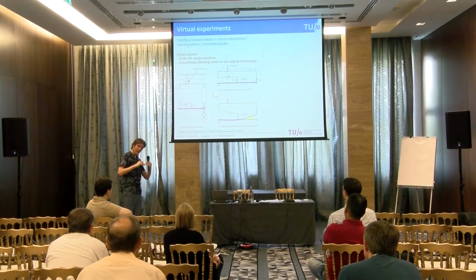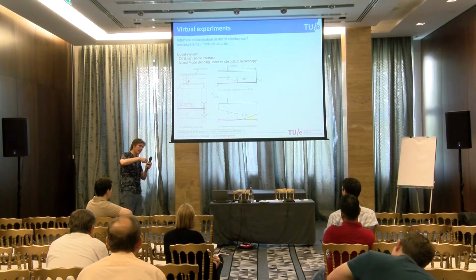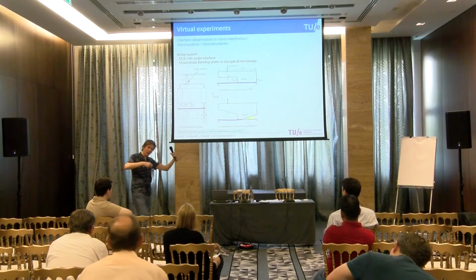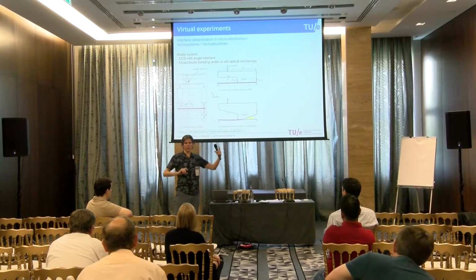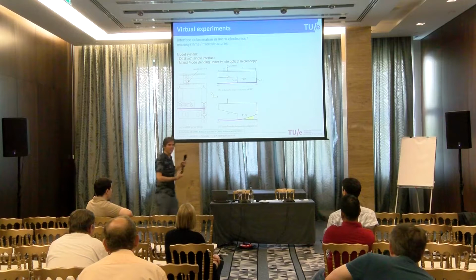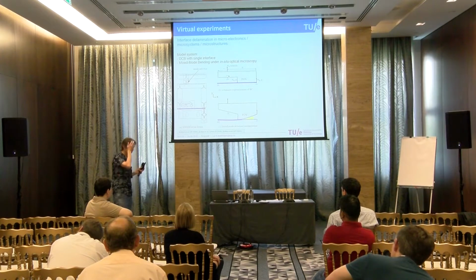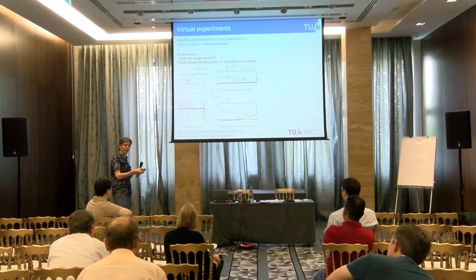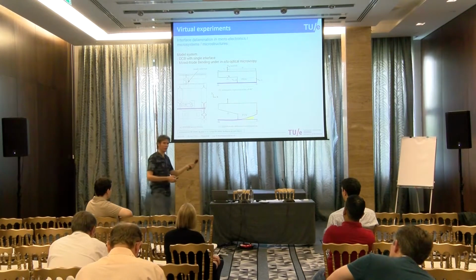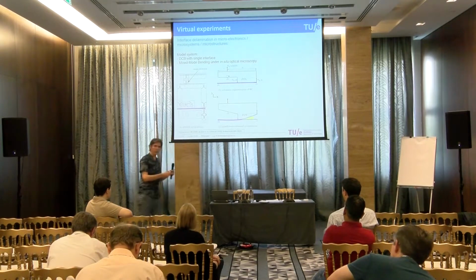Zeta is an interface parameter. It's an interface parameter explaining the mode mixity, how much larger the fracture toughness in mode 2 is compared to mode 1. And I also didn't invent the parameter zeta for that. That's coming from the cohesive zone, the typical type of Van der Bos. A previous member of my group developed a cohesive zone model, and it had 3 parameters: fracture toughness in mode 1, the critical opening displacement, and also the zeta parameter.